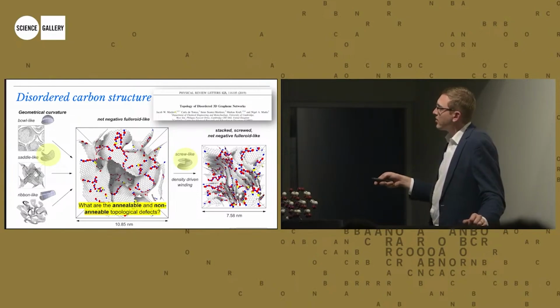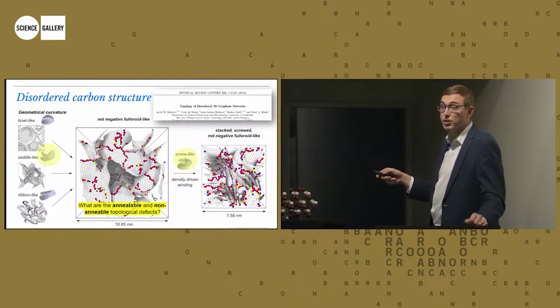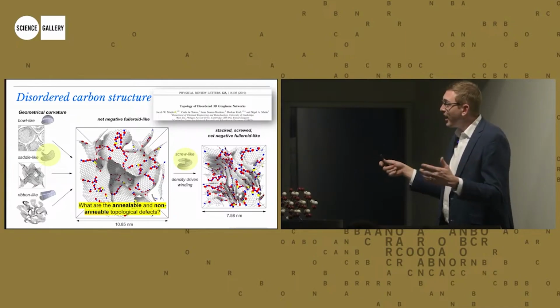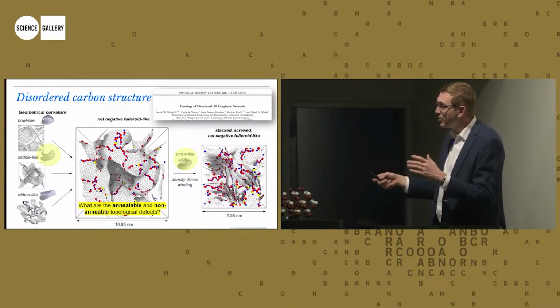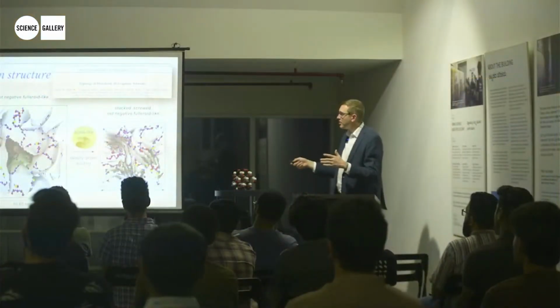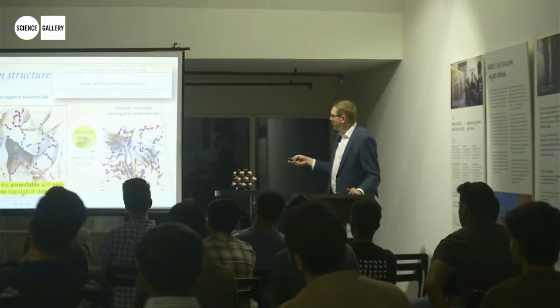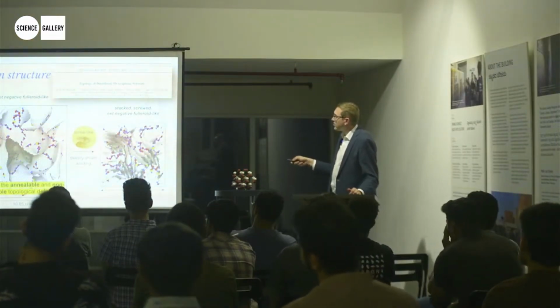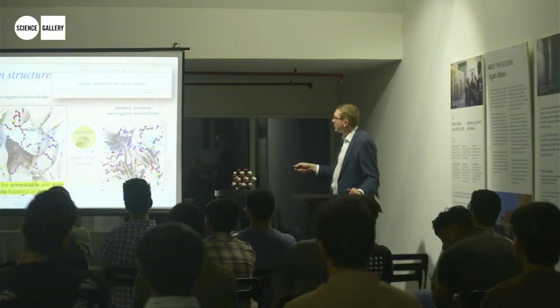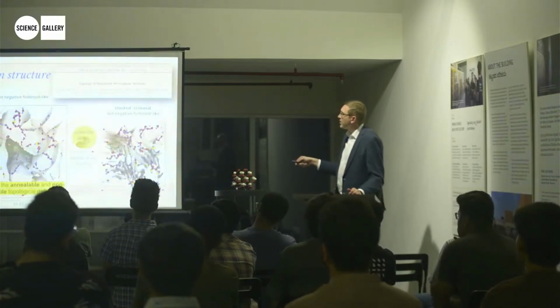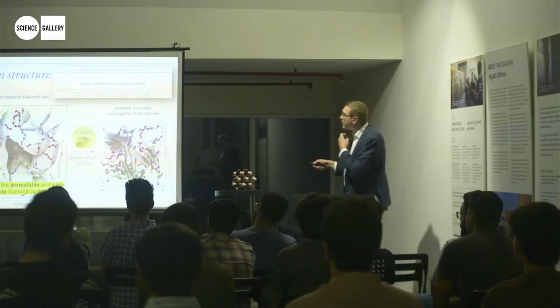And what we found is that these structures all possess, so I should mention, these were generated in a supercomputer, completely self-assembled. We put the atoms in randomly and let the computer anneal it, like you're cooking it, but in the computer. The computer jiggled the atoms, bonds formed, bonds broke, and this self-assembled. If you were to run it again, it would be different, but it would also sort of be the same disordered structure. And what we found is that there are screws, or these spiral defects, in this structure, and that there are these sort of non-annealable defects here. We'll come back to those.